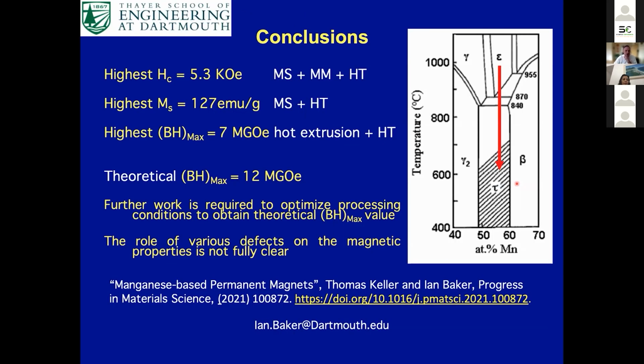So I just want to conclude by saying that there have been lots of different ways of processing manganese aluminum, and the highest coercivity I've obtained is this 5.3 kilo-oersteds, which was produced by melt spinning plus mechanical milling followed by heat treatment. And in a different work, the highest saturation magnetization was obtained of 127 emu per gram, which was developed simply by melt spinning and heat treating. And the highest energy product was obtained by hot extrusion plus heat treatment. But even this best value that anybody's obtained so far is actually below the theoretical value.